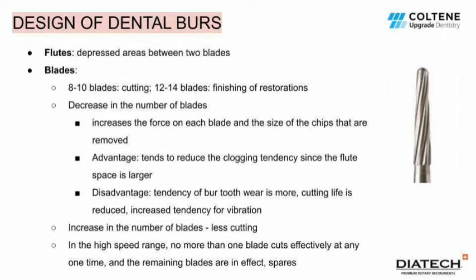A decrease in the number of blades causes an increase in the force on each blade and the size of the chips that are removed. The advantage of a lesser number of blades is that they tend to reduce the clogging tendency of the flute since the space between two flutes is larger, while a disadvantage is that they increase the tendency of tooth wear of a burr, resulting in a reduction in its cutting life and an increased tendency for vibration. An increase in the number of blades, on the other hand, causes less cutting of the tooth material.